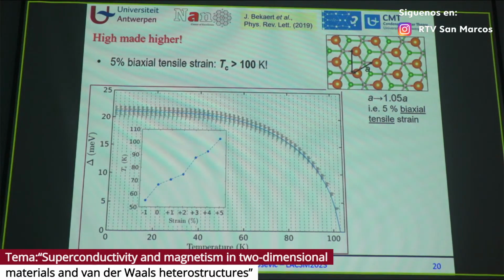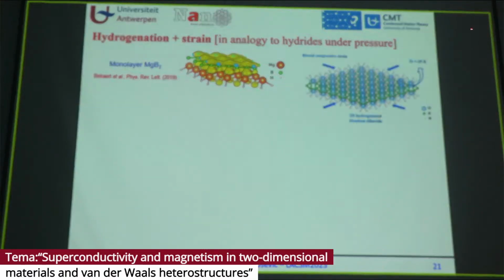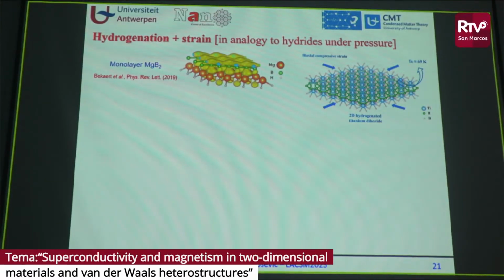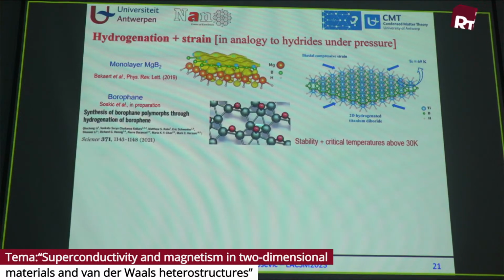Now, somebody might say, yes, this is only for this particular material. Well, it's not. This hydrogenation, or as some people call it, phonon doping, has been proven very effective for example in titanium diboride superconductivity. Then in borophane, the borophene is not superconducting. Borophane is superconducting, and it has been recently fabricated at Northwestern University in the US with critical temperatures around 30 Kelvin.